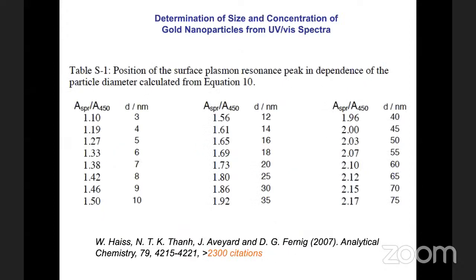This work is very highly cited, so it's very applicable, and I'm very mindful that a lot of colleagues from developing countries don't have a lot of equipment. For example, when you want to look at the nanoparticle as I have shown earlier with the TEM image, then you need very expensive equipment with highly trained personnel. But in this case, you can use UV-Vis, a very simple spectrometer, to find out the absorption, and here's the absorption at 450 nanometers. You do the ratio, and provided your nanoparticle population is monodispersed, then you can find out the size of the nanoparticle. And now it has nearly 3,000 citations.